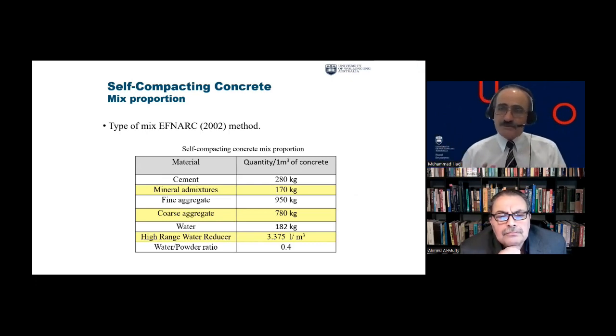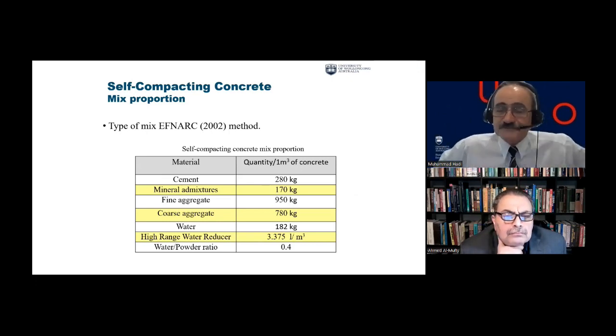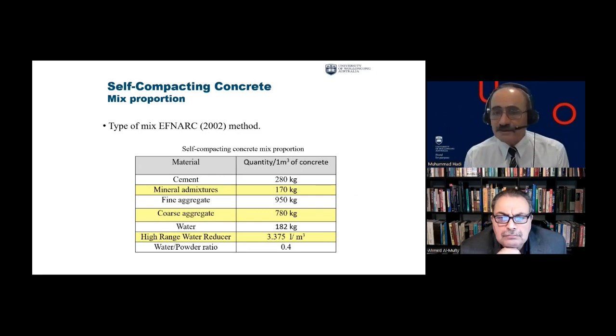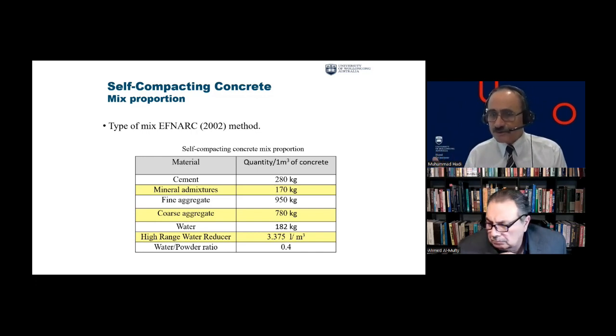Now let's go back to the self-compacting concrete. In self-compacting, cement is not more. Then we added some minerals, fly ash and the like. Then the main thing, the coarse aggregate is small, whereas fine aggregate is large. Coarse aggregate, 10 millimeter maximum. This is what we use because of the size of our samples. Then we had some high range water reducer and water powder.